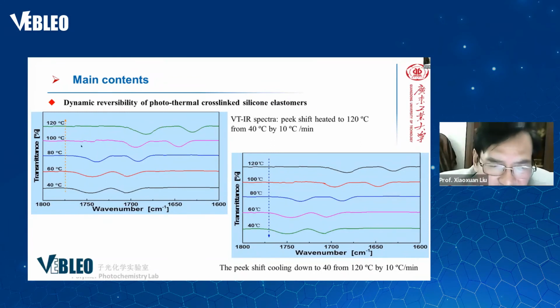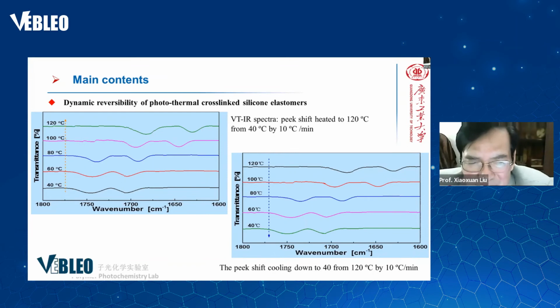In the left figure, the temperature is increased from 40 degrees centigrade to 120 degrees centigrade. This is heating. Then as it cools down from 120 degrees centigrade to 40 degrees centigrade, it is reversible, as the peak shifts back.